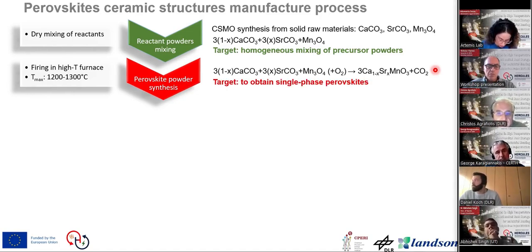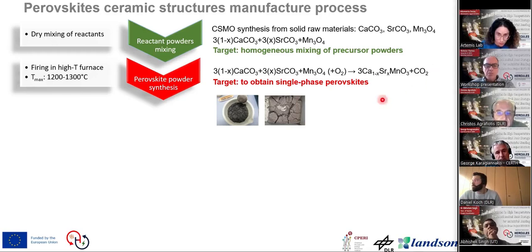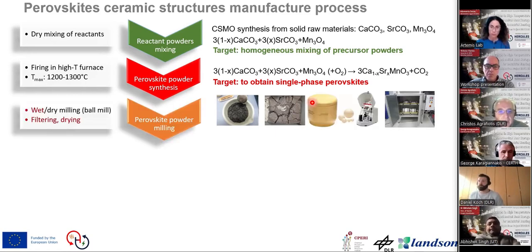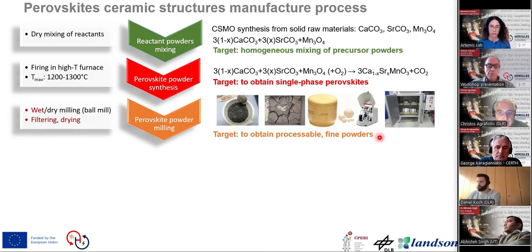If we click here, for instance, we see that the issue is to obtain single phase perovskites, but because of the high temperature, the powder that comes out is heavily sintered into single chunks sometimes, and this has to be milled first to bigger pieces that can be handled. Then, by typical ceramic processing milling techniques, we can either dry or wet mill it in small lab quantities or in larger ball mill furnaces. The idea of this milling step is to obtain a processable fine powder for the next shaping techniques.